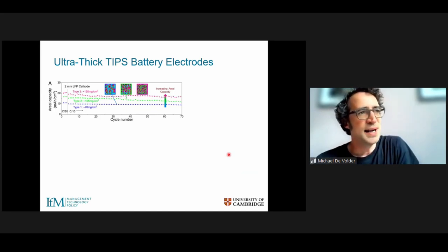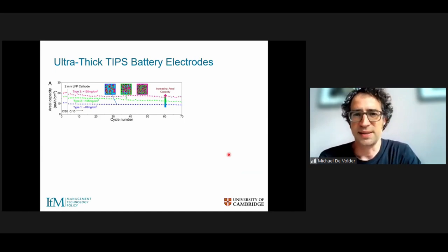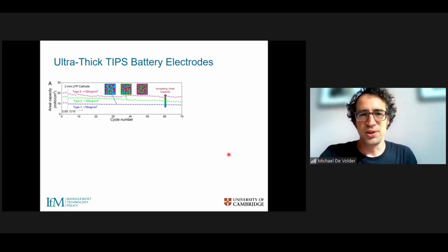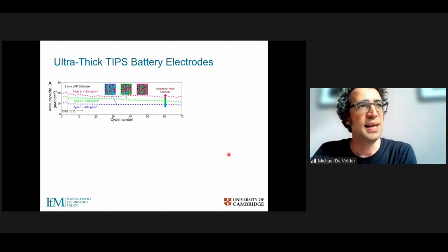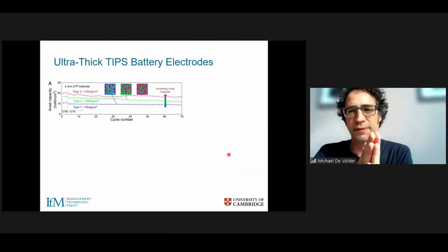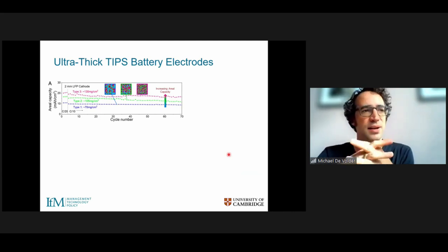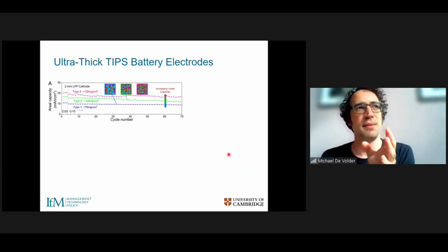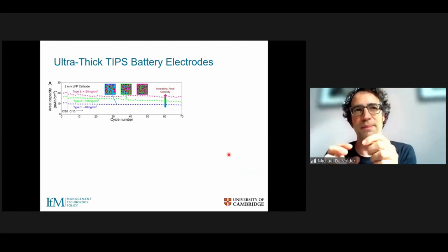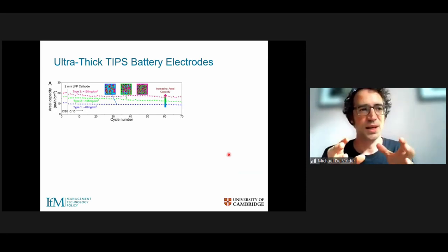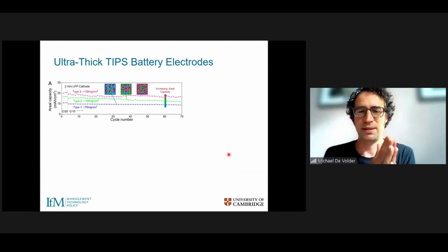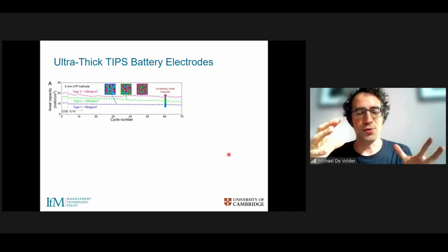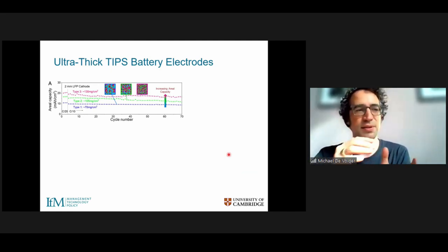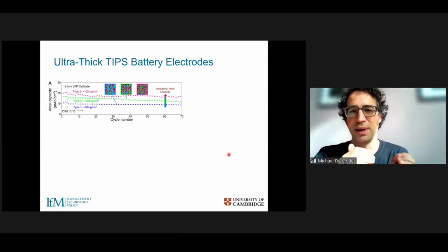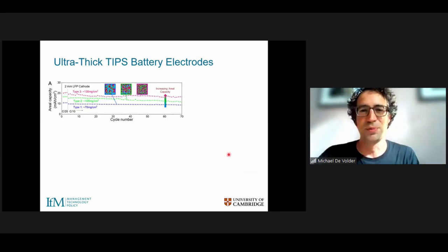Then we started trying to control our phase segregation process a little bit more. The challenge we had initially is that as we carried out our phase segregation process, the voids that were created between the active material and the electrolyte phase were quite big. So the amount of electrolyte was very large compared to the amount of active material. Now, in a real battery, you want to cram as much active material together in a small volume as possible, typically, because otherwise your batteries just become too bulky.